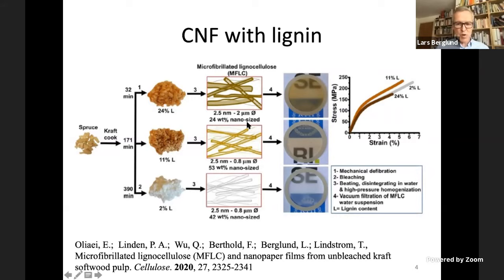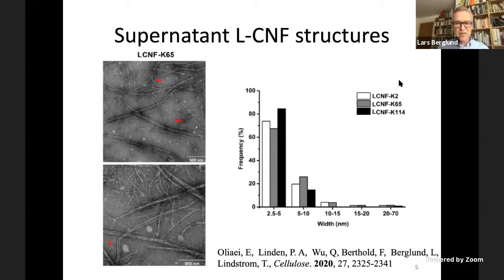And the center composition here with the 11% lignin, so kappa 65, is actually very suitable to make fibrils from. And perhaps interesting is also, if you look on the right-hand side here for the stress-strain curves, the properties of these films are actually not that far away from the best fibril films that we can make from, for instance, TEMPO fibrils. So if you look at the supernatant structures here, so basically you carry out your kraft pulping, and then you use traditional microfluidizer homogenization.